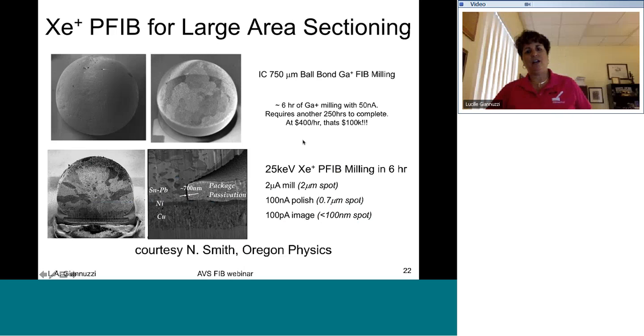Compared to using a xenon plasma FIB, you can do this in about 6 hours with first 2 microamps, then a 100 nanoamp polish, followed by a 100 picoamp image, all within 6 hours. And obviously, there's a great cost reduction just in instrument time itself. So again, there's the big advantage to using the xenon plasma FIB for larger FIB-milled regions. Your realistic limit in a gallium FIB is probably 100 microns at the upper level. Really, 50 microns is probably more reasonable. Anything larger than about 50 microns is really not a gallium FIB job, unless it's the only thing you have and you're willing to sit there long enough to mill through very large materials.